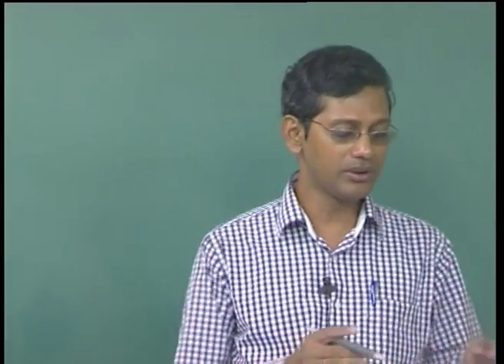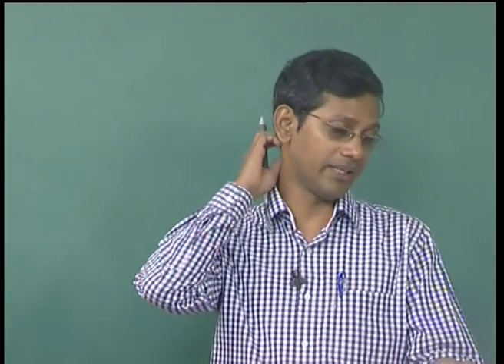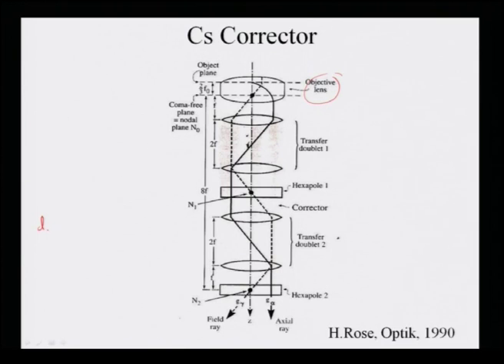So, as you can see, when the CS is corrected, the resolution of the microscope will depend only on the chromatic aberration. Therefore, resolution can be written, when CS is corrected, as the square root of (delta E by E) times lambda CC, where CC is the chromatic aberration constant. So, when CS is corrected and delta E is 0.3 eV in a 200 kilovolt microscope, we can clearly see d will be approximately 0.8 angstrom.